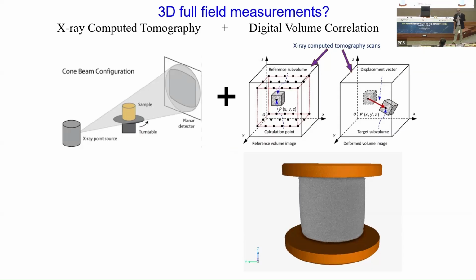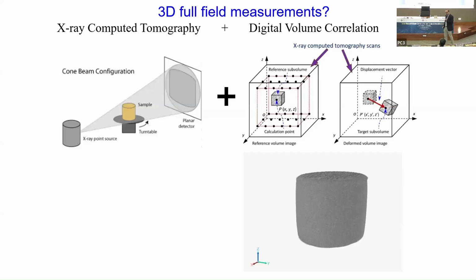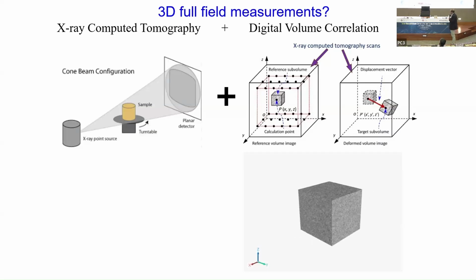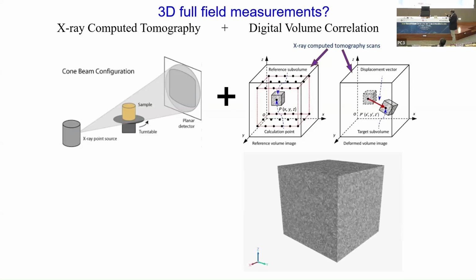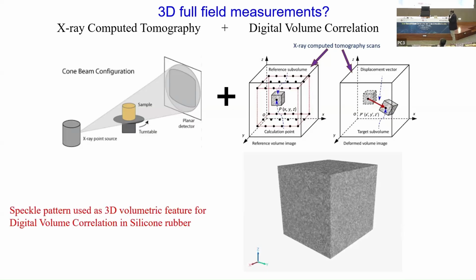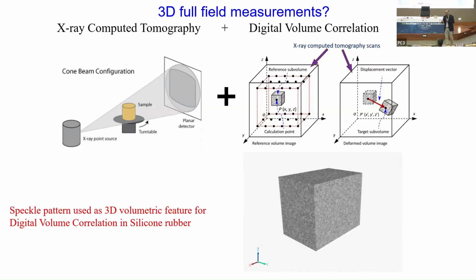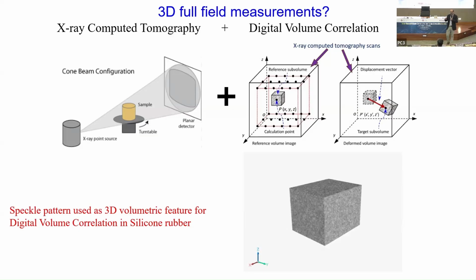Now, I'm going to take a material which has very little microstructure, which is silicone rubber. But when you look at it very carefully, you'll see that it does have a microstructure. So this is a piece of silicone rubber. And if you go deep into it, you'll see it has this kind of a microstructure. And because it has essentially what we call a speckle pattern, it's this speckle pattern that we will use to basically correlate one image to another image. And that's how we will be able to construct a displacement field in 3D.